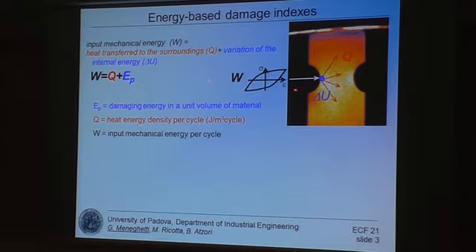So, as you know, when you apply fatigue loadings to a notched component, at the critical point you have some energy consumption, so you provide some mechanical energy to the material, and some of this mechanical energy provided to the material is dissipated as heat, and some is stored by the material. In the literature, EP is the so-called stored energy of cold work. Now, of course, the probably more efficient idea would be to measure the stored energy of cold work, because it is responsible for fatigue damage and crack initiation. But we know that most of the mechanical energy expended in fatigue is dissipated as heat. So this energy balance looks like, say, 100 is the mechanical energy expended at the notch tip, 99 is dissipated as heat, and so the stored energy is only a small fraction.